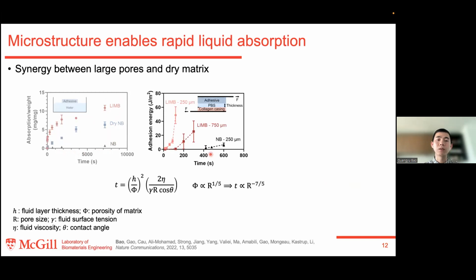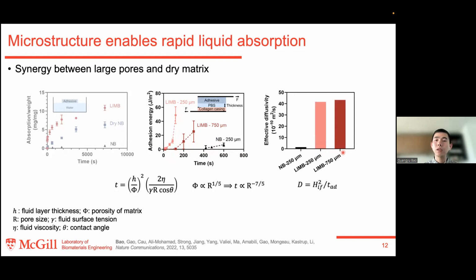We also measured the adhesion energy kinetics. For our porous and dry matrix, it starts to form adhesion within 15 seconds upon contact with the wet surface. However, the non-structured bioadhesive, which is not dry and not porous, doesn't form any adhesion within 400 seconds upon contact. And if we calculate the effective diffusivity, our porous and dry adhesive shows a much higher effective diffusivity compared to the diffusion-driven non-porous counterparts, which also explains why our adhesive can so effectively remove the interfacial barrier, which is the liquid on top of the tissue surface.